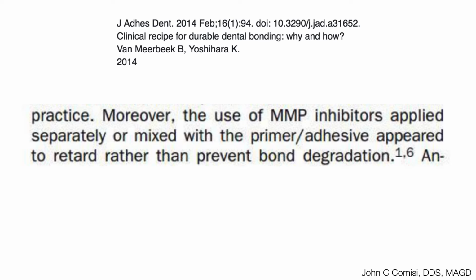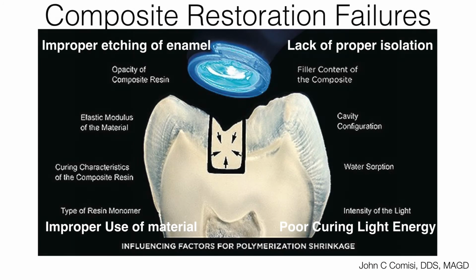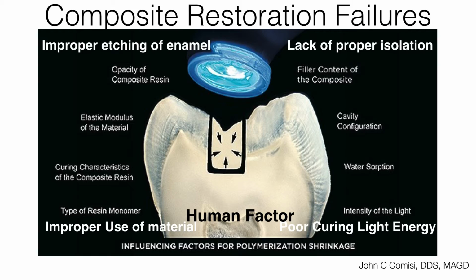Dr. Bart Van Meerbeek makes this important comment in this paper from 2014. Moreover, the use of MMP inhibitors applied separately or mixed with primer and adhesives appeared to retard rather than prevent bond degradation. Now, of course, there are many factors that come into play in our composite failures, many of which are listed here, including light energy, correct placement of the light, cavity configuration, opacity of the material, the resin monomer, but perhaps the biggest factor is the human factor.